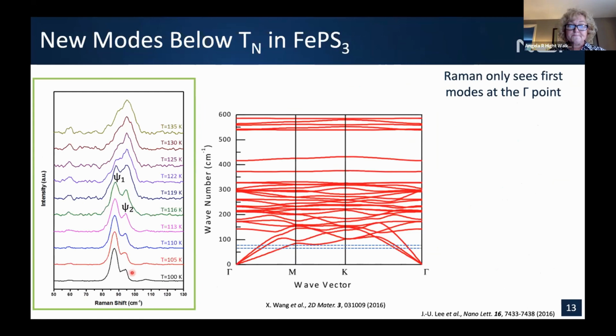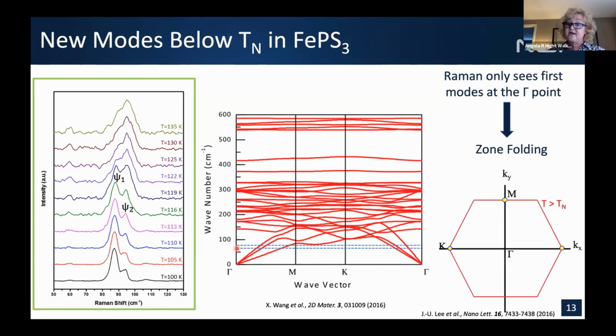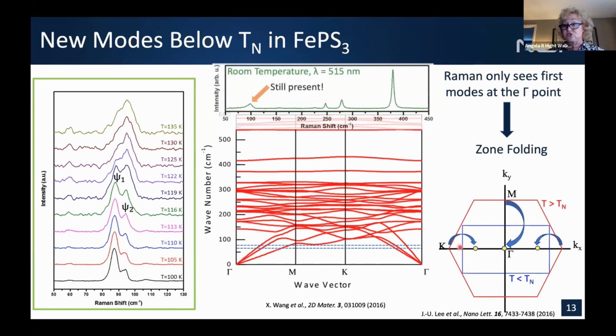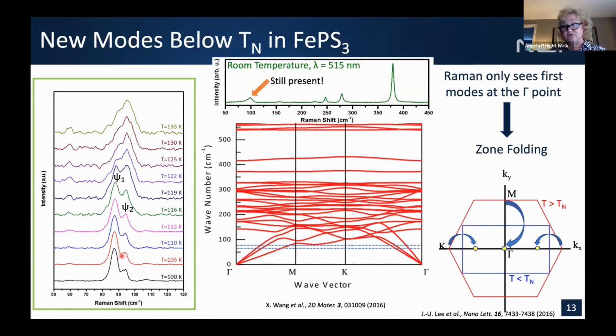What's interesting, if we look at DFT calculations spanning the Brillouin zone, we see that there's really no features at gamma. So just to remind you, Raman is typically looking at phonons at gamma equals zero, at the zero angular momentum. There are opportunities to see other phonons, and that can come in with zone folding. And in this case, these two features that we're looking at called Psi1 and Psi2, we believe, in fact, that is what's happening. So just as a bit of a cartoon here, we believe that these K points are not folding in, but rather the M points do. And that's giving rise to these two features.